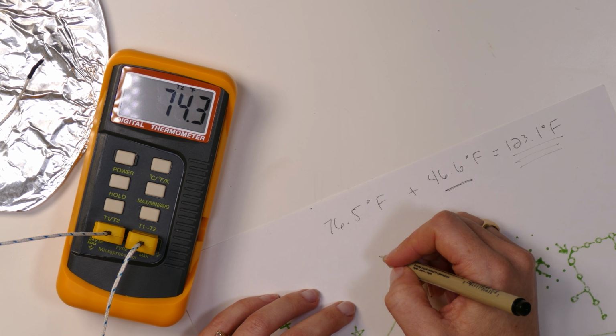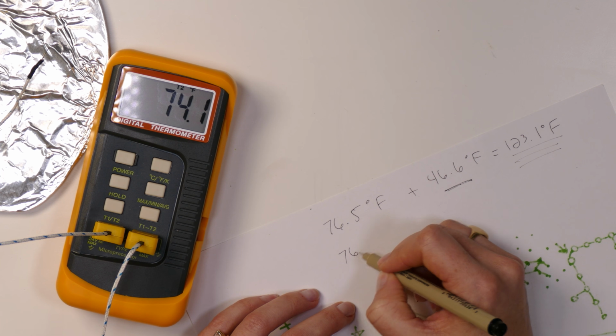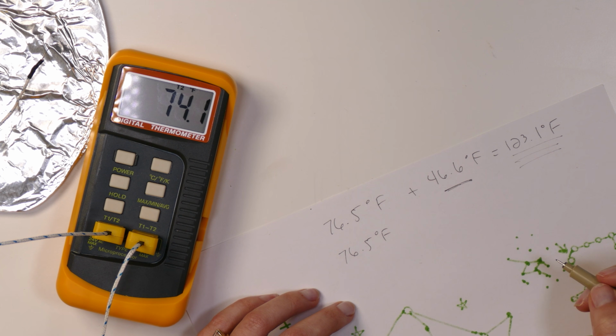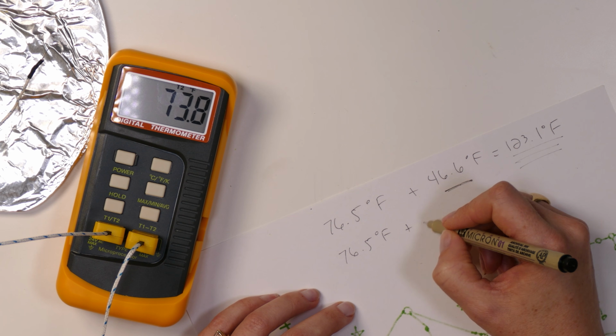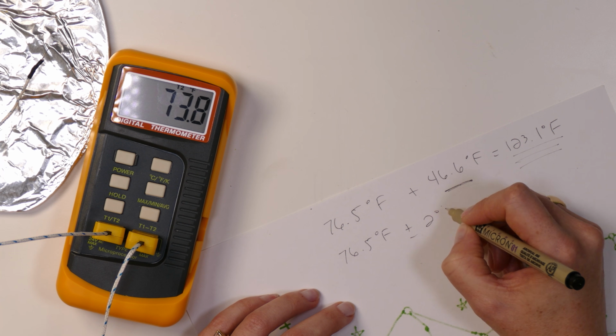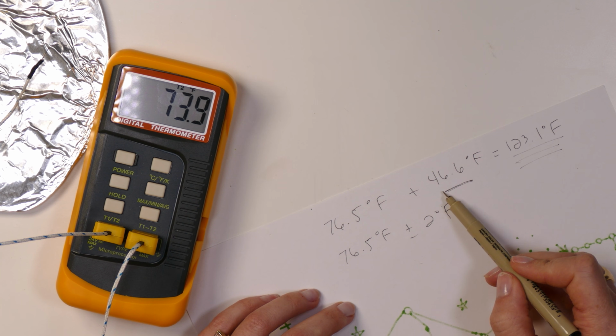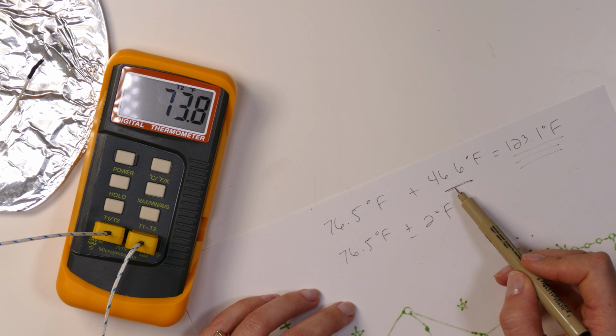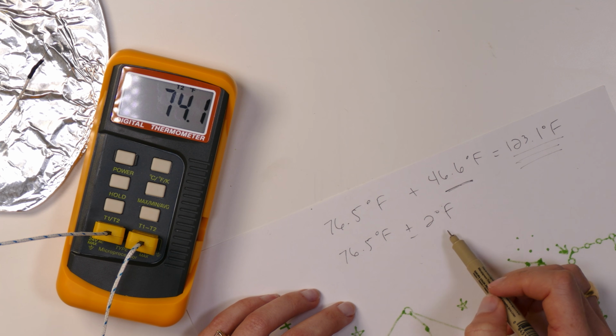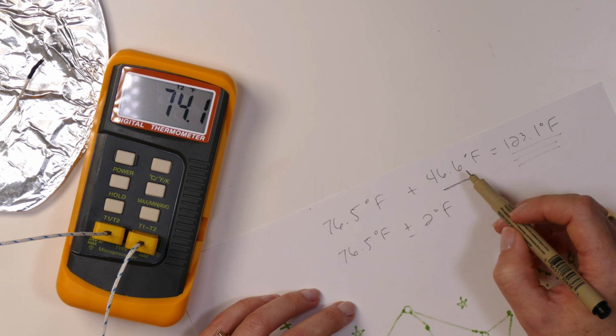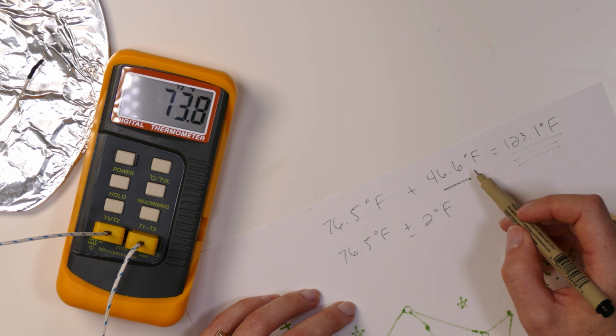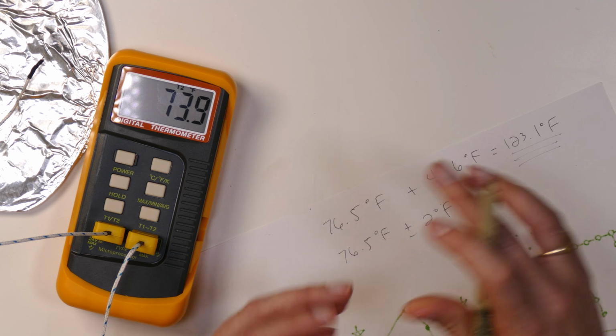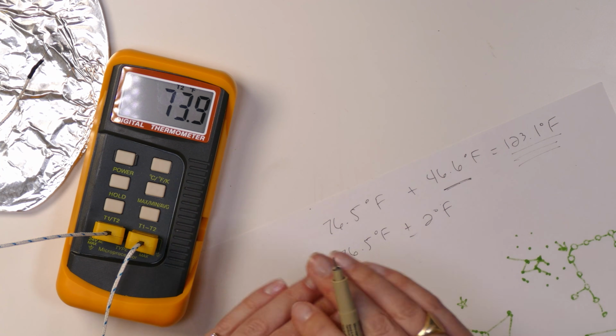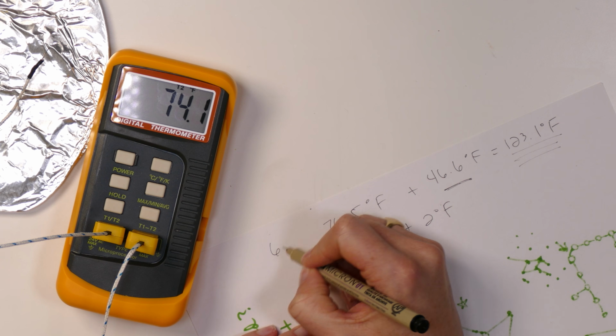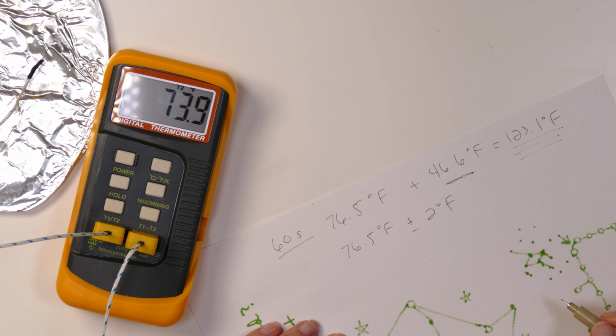The other cool thing is when we cured again, obviously again, our ambient temperature was something like 76.5, but the plus or minus on the gel was only about 2 degrees Fahrenheit. So that means that the gel fully cured during the first 60 seconds of lamp exposure. And because I didn't get another heat spike, there was no more bonding happening. There was no more monomers bonding or anything like that. No more molecular bonding happening, which means no more heat is being released. Therefore, all of my bonding has been completed. So this tells me that a 60-second cure in this lamp actually fully cures this product.